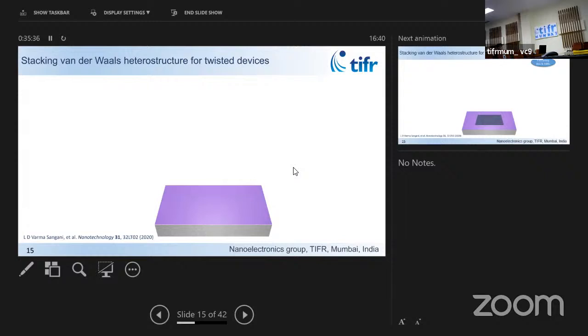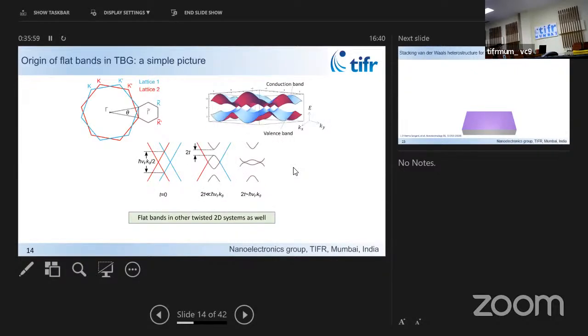So often when I talk about this, people are curious how one makes this. It's somewhat subtle because you cannot arbitrarily pick up two layers of material which are one atom thick and align them to an accuracy of 1 degree, because you want this angle to be very, very small. I guess I didn't say something here: these flat bands arise when the hopping between the two layers and the hopping between sites in the same layer become comparable. That's when the flat band arises.